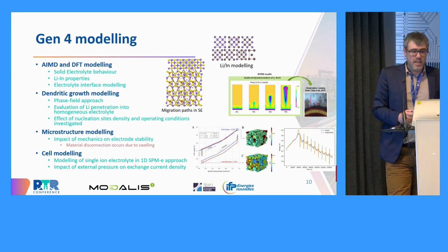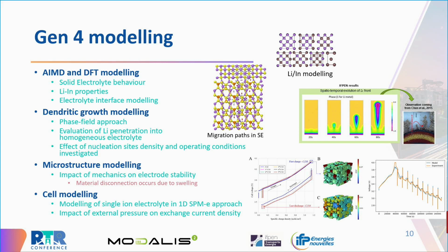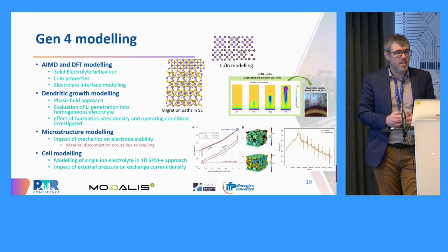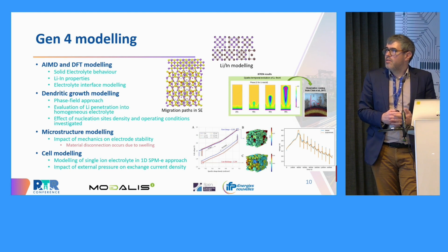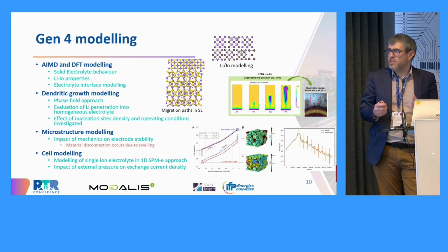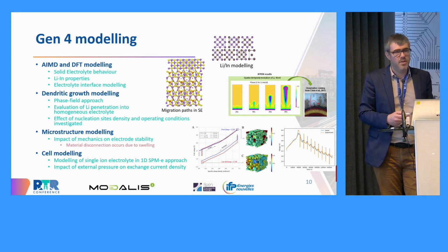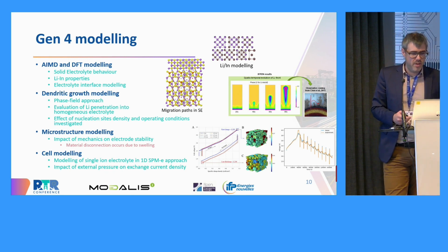On the modeling side, we also did some molecular and ab initio modeling in order to understand the behavior of the electrolyte, how the lithium ions are transported in the electrolyte, in order to put them into a full-scale model. What are the properties of the lithium indium, which was not the main topic in the beginning of the project, and also what are the main properties of the interfaces. Interfaces between NMC and argyrodite, and interfaces between argyrodite and lithium indium, and argyrodite and lithium, which showed some obvious result at the end, but it was possible through calculation to validate what was observed in real life, especially that lithium indium was far more stable compared to lithium towards argyrodite.